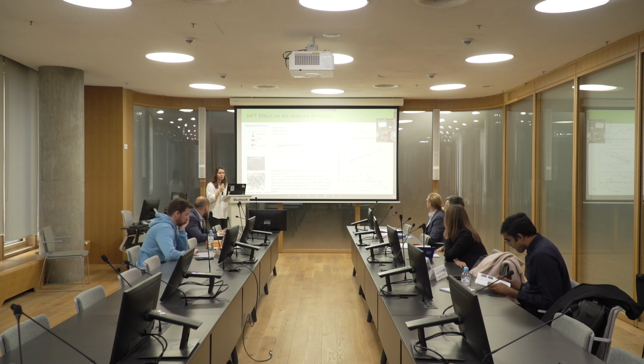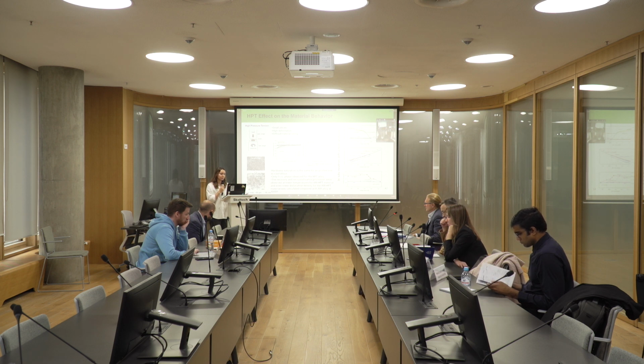So maybe the formation of other phases is possible, but in case of the sigma phase, we can just translate the result from the 5-component system to this one, because the as-cast materials don't present the formation of this sigma phase for this 4-component system. But maybe the higher deformation process leads to the formation of additional phases, including the sigma, so we didn't observe it.